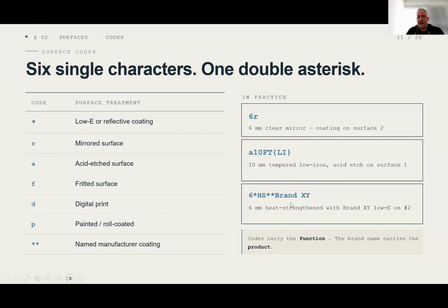But it allows you to have different codes. You could have a 1-inch unit with different low E and still be able to specify it by changing the trailing descriptor of that coating. Above it, we have, again, 10 mm tempered, low iron, acid etch surface 1. This one, we have 6 mm clear annealed. It doesn't say the type or the material, so we know it's clear annealed with mirror on number 2. So this is how these would be read.